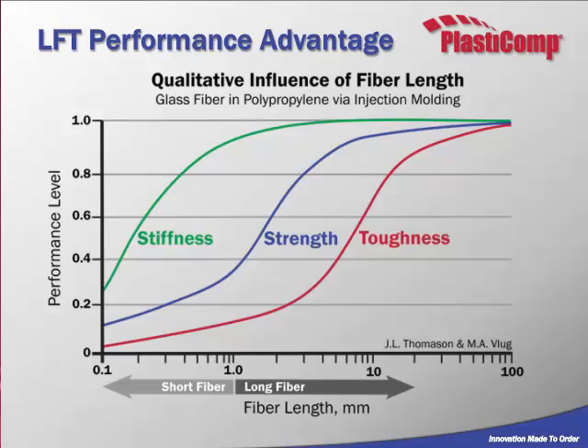So again, fiber length doesn't play a big part on stiffness, but you can see that as you start to extend out into the 1 millimeter length and higher, you do get somewhat of a strength increase. Toughness, as you push out into the 4, 5, and 6 millimeter length, starts to become an exponential increase. And again, that's where long fiber, if processed correctly, can give you an added benefit. You'll get that stiffness, but you're going to get that added durability that short fiber just can't give you, especially at low temperature.